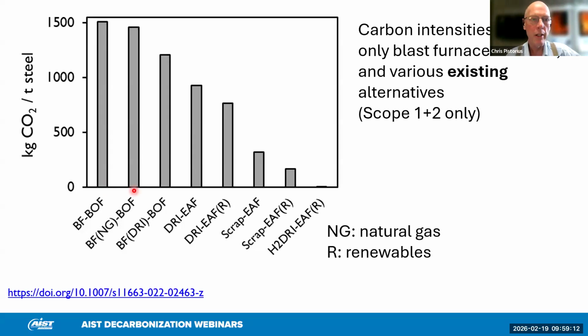If one maximizes natural gas injection, you can decrease that a little bit. In part, that is because one needs more oxygen enrichment, and producing oxygen isn't necessarily carbon-free. If you charge the maximal amount of metallic iron you can, you can see that really decreases the CO2 emissions substantially. This includes the CO2 emissions from making DRI using natural gas. The DRI EAF one, again, there are plants doing this currently. That's around 900.